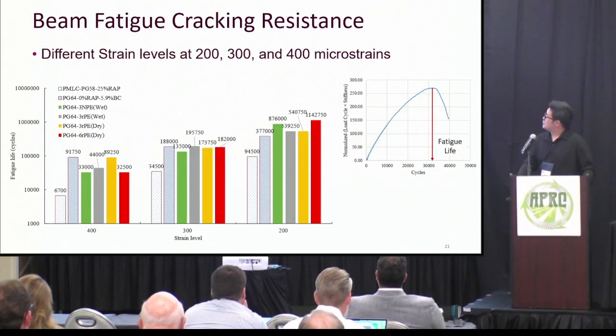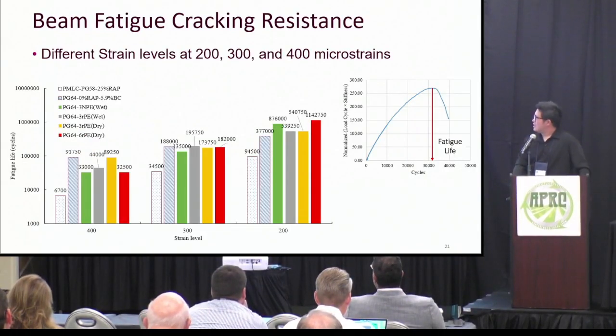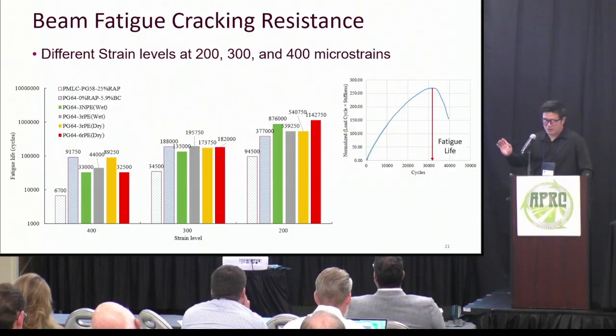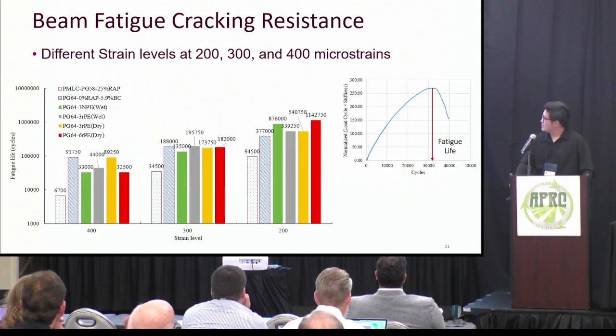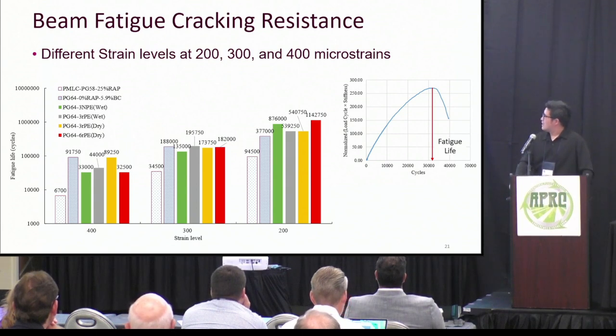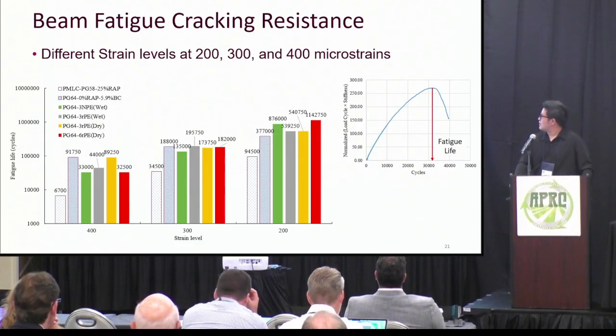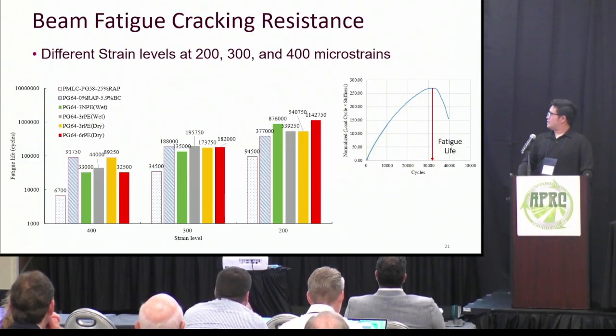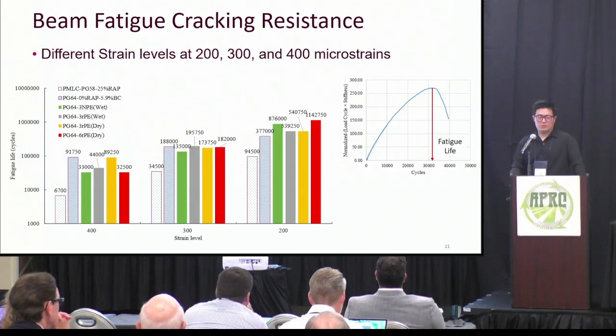And then we did the fatigue cracking resistance test. We did the cracking test at different strain levels, for example 200, 300, and 400 microstrain. It shows 3% recycled PE mulch using the dry mixing method has more balanced fatigue resistance performance.